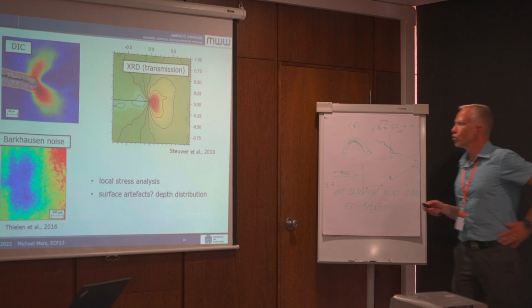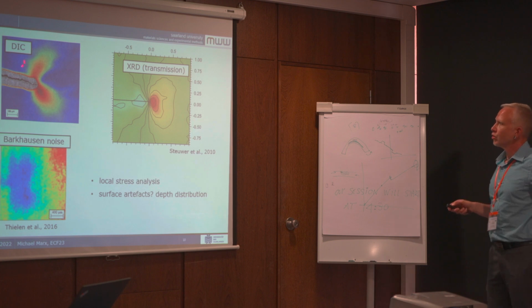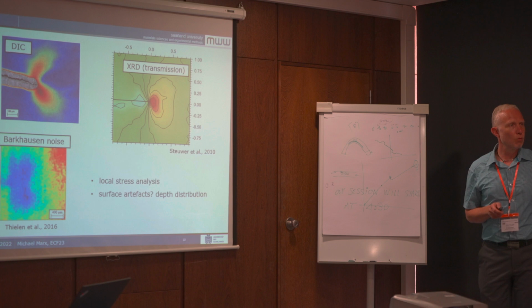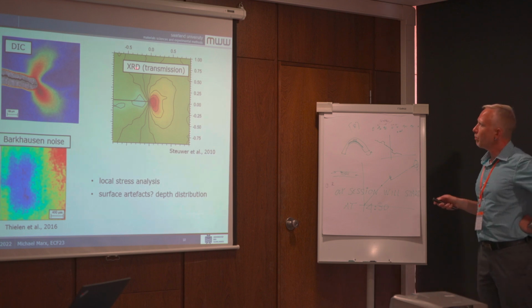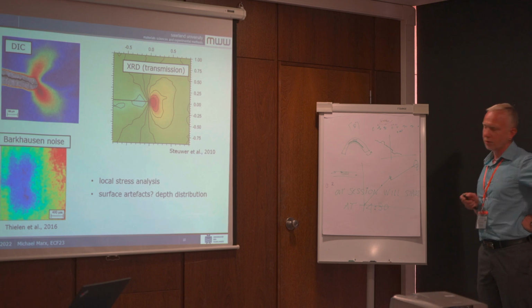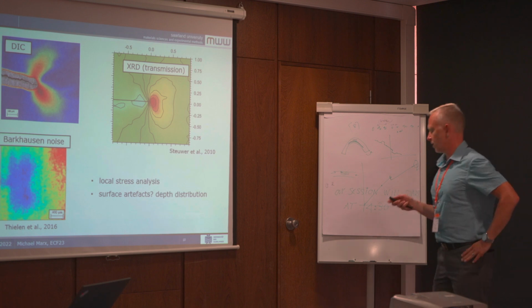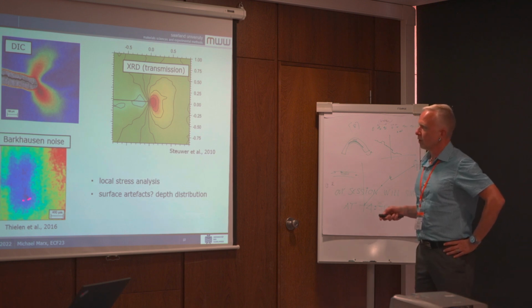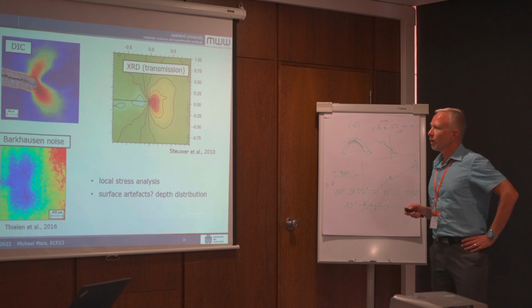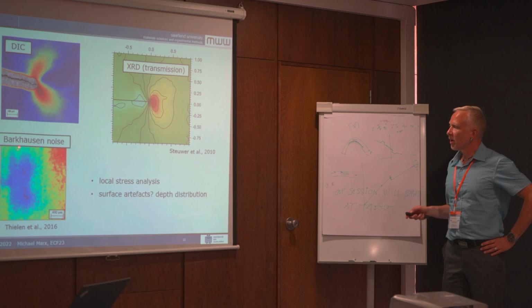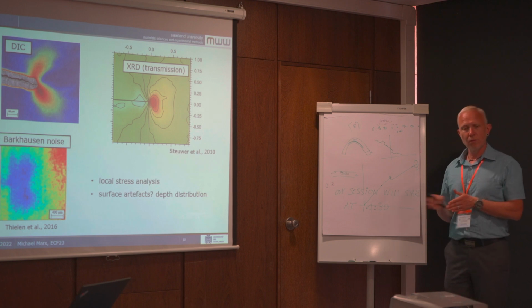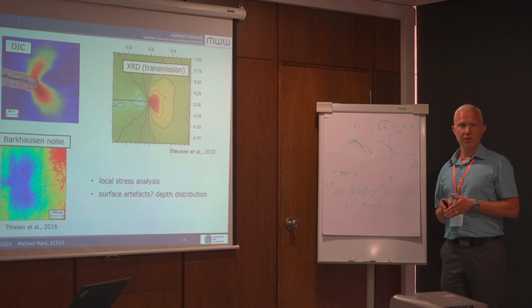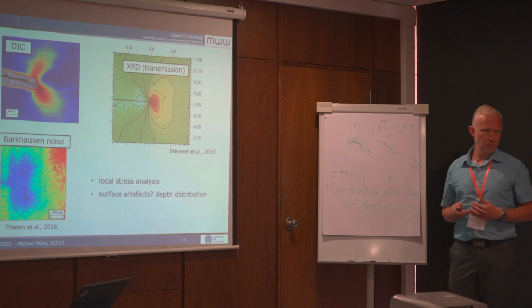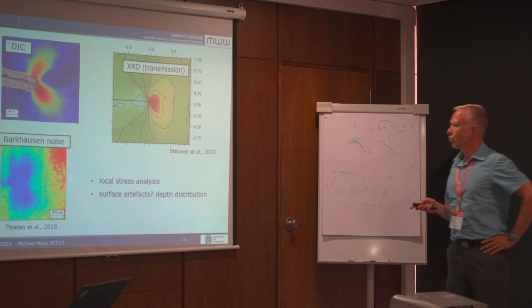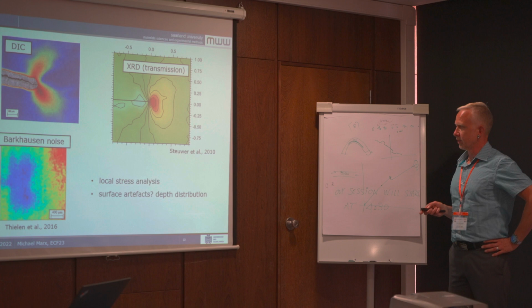If you want to measure the plastic zone, the stress distribution, you have different options. You can measure it by digital image correlation, then you get only the information from the surface. Or you can measure it by XRD in transmission, then you get the information through the whole specimen, but you can only do this for very thin specimens. Or, what we have also done, we measured the stresses in front of the crack tip by Barkhausen noise, but this is not so easy. You have also some information of the depth, not only surface information, but this is quite complex to calibrate, so it's not so easy to get the information from this.